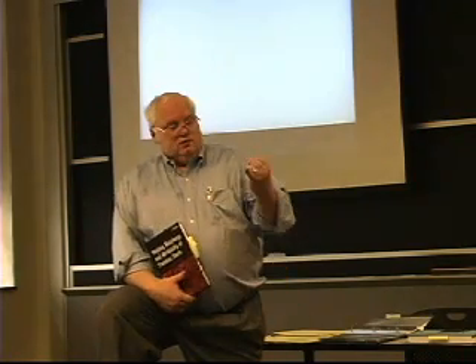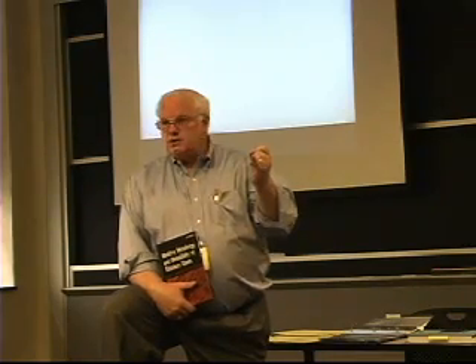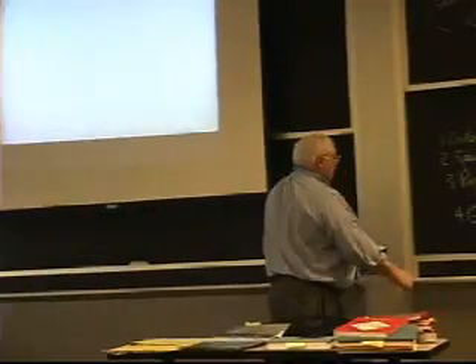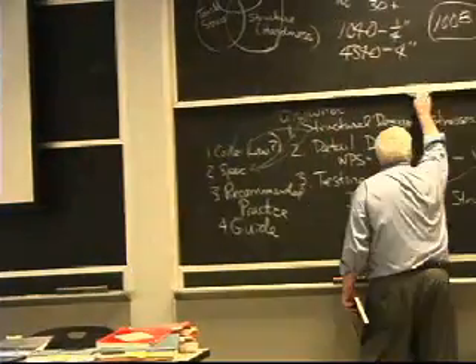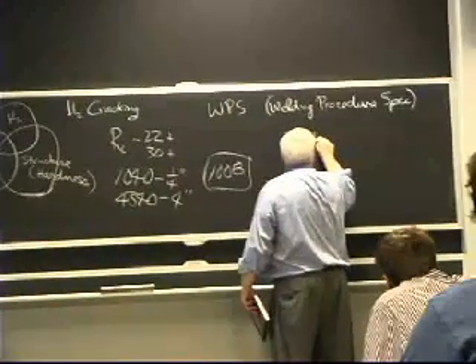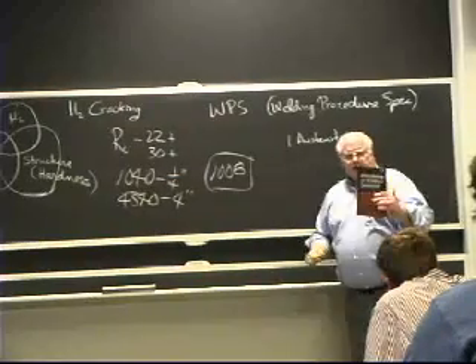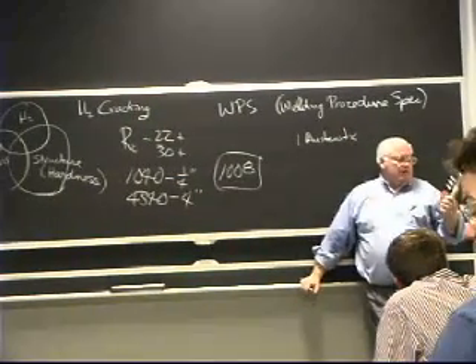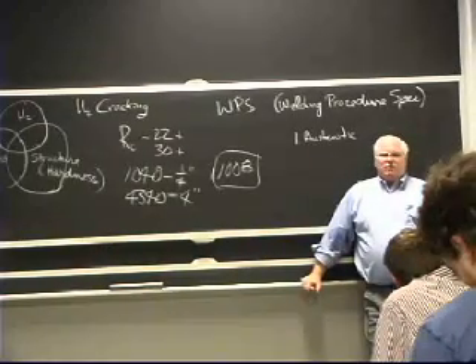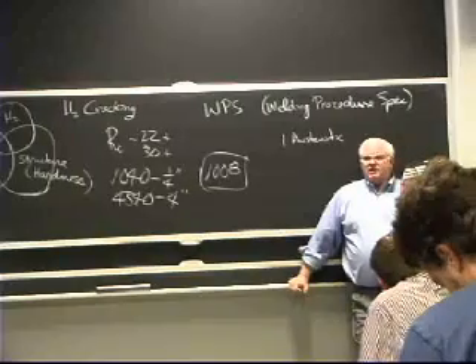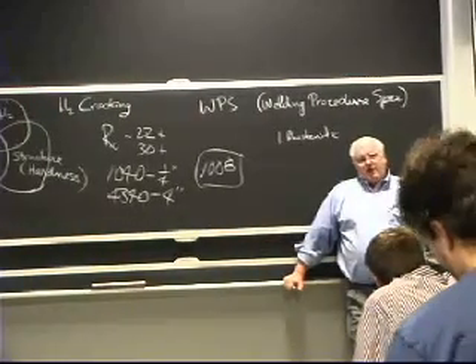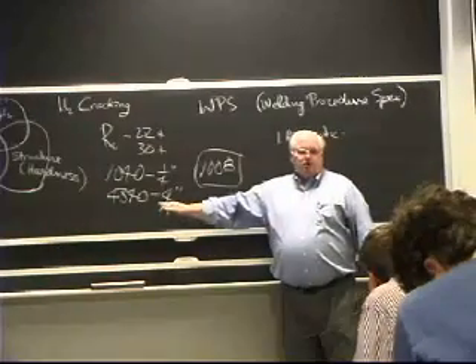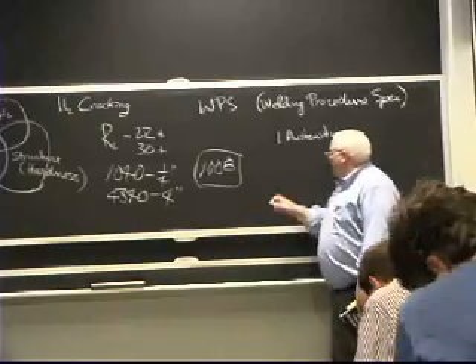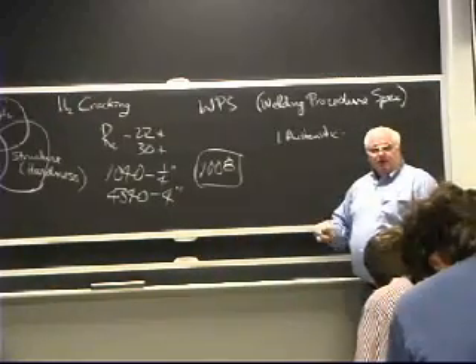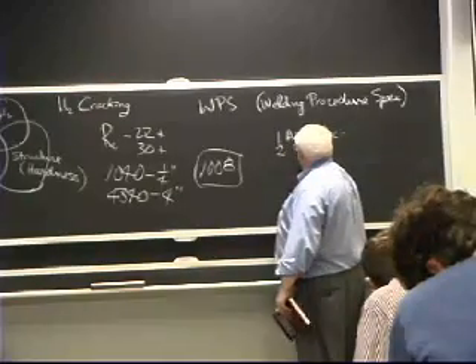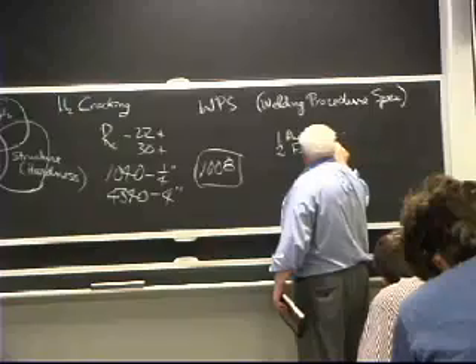And so there's a whole book on welding of stainless steels, and I'm not going to go through all the details. There are three, well actually they list 4 general types of stainless steels. One is austenitic, which is non-magnetic, which is very easy to weld. However, I think I told you once before that I found that even though stainless steels are only about 5% of all the steels made, they're about 30% of all the problems. Because everybody thinks that stainless steels will never oxidize and will never corrode. Well, it depends, okay? Turns out austenitic stainless steels are relatively easy to weld in terms of a welding procedure specification, the recipe for actually making the weld. But then making a weld that won't corrode is another complexity to it, and so that makes things a lot harder. Then there's ferritic stainless steels, which are magnetic.